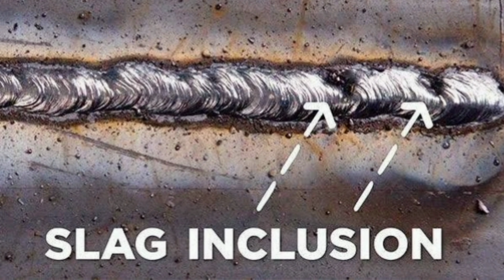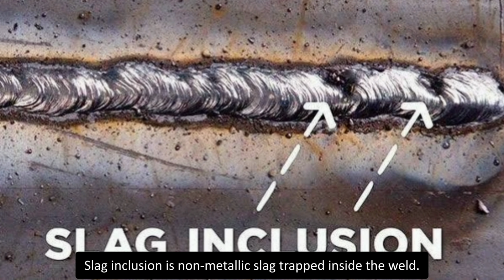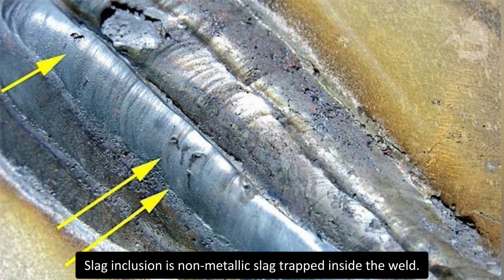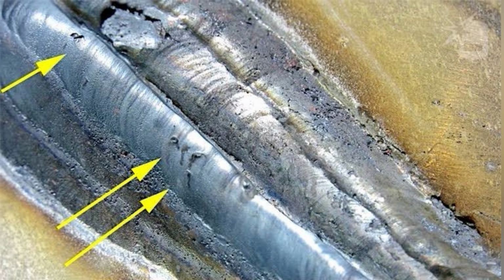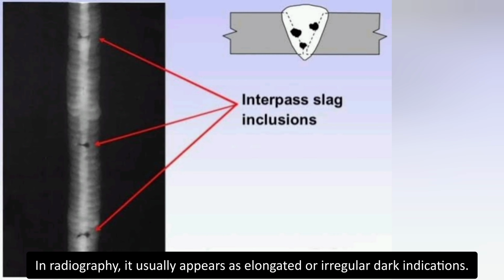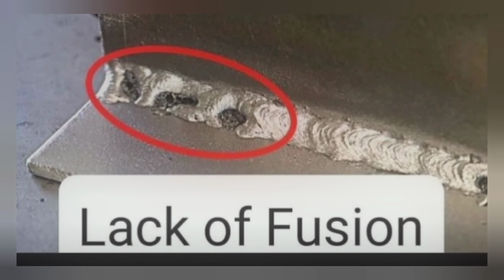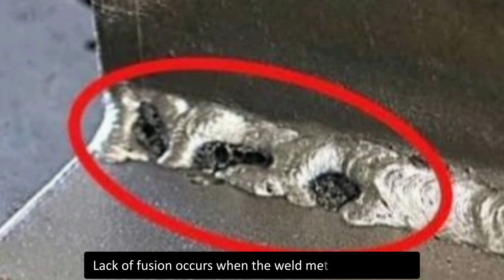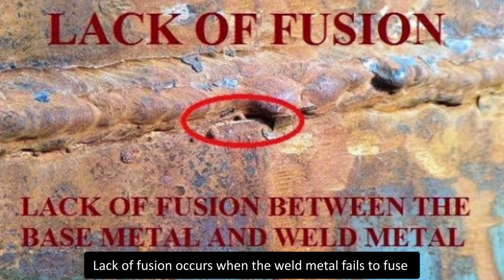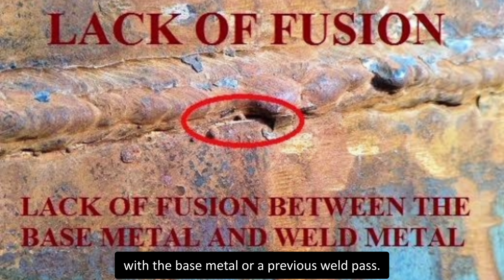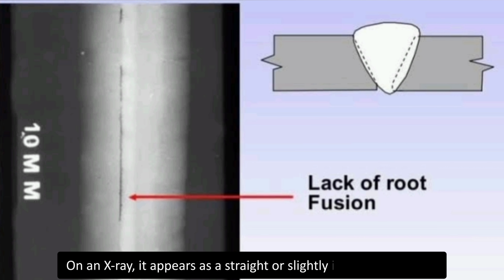2. Slag Inclusion. Slag inclusion is non-metallic slag trapped inside the weld. In radiography, it usually appears as elongated or irregular dark indications. 3. Lack of fusion. Lack of fusion occurs when the weld metal fails to fuse with the base metal or a previous weld pass. On an X-ray, it appears as a straight or slightly irregular dark line.